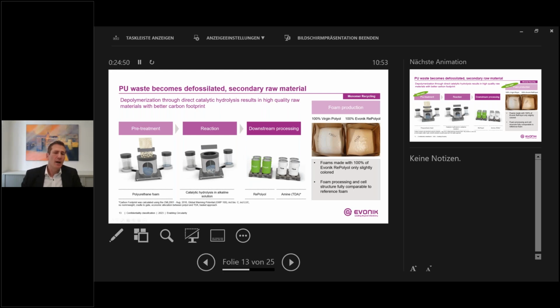So we are able nowadays to use the used mattresses to convert the polyurethane foam into monomers. This means the polyol and the amine, which are the main components of such a polyurethane formulation. And this is a chemical recycling process, really a very challenging recycling process. And we are really proud that the polyol, for instance, can be used at 100%, and the performance of the foam, the mechanical properties, are more or less the same compared to the virgin polyol.